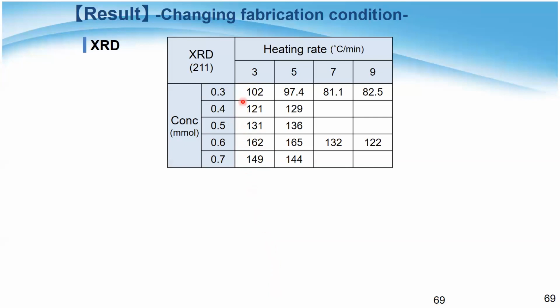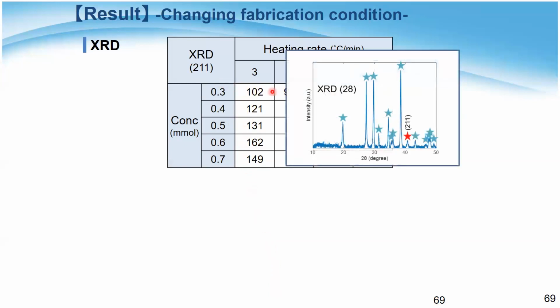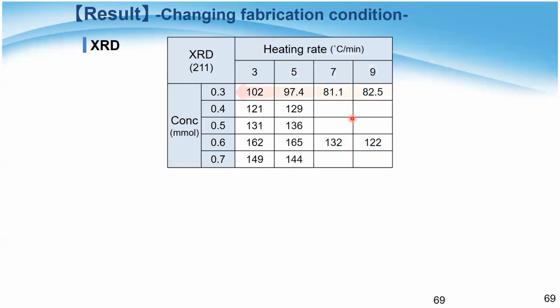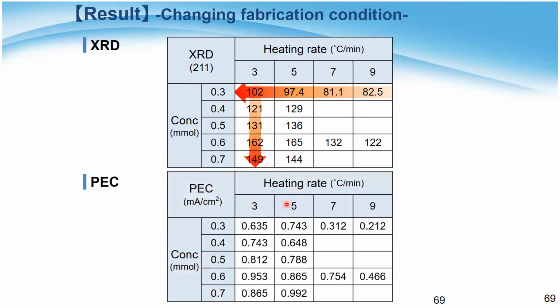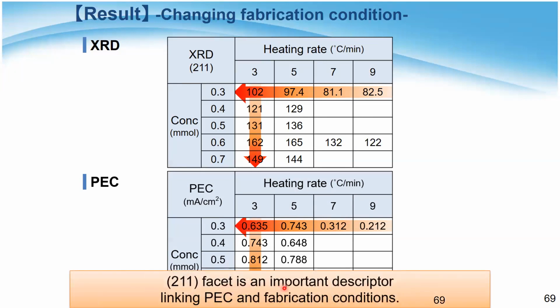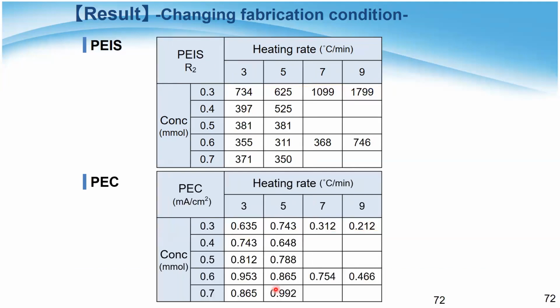And then looking at the XRD peak 211 facet, which is here, this minor facet was controlled by heating rate and the concentration, like this trend. And again, similarly, PEC performance was also controlled with the same trend. So we can optimize by reducing heating rate and increasing concentration. So the 211 facet is also an important descriptor connecting the PEC performance and fabrication condition.